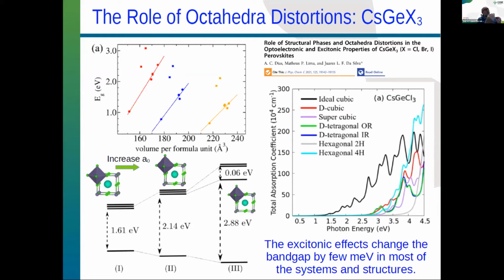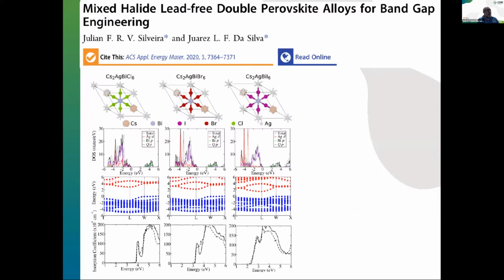However, if some of those grains stay in the hexagonal phase, they are going to contribute a larger band gap. That is quite an important point. We also find that excitonic effects play a minor role in this particular case. We use a tight-binding approach combined with DFT, as was shown yesterday by Alexandre Cavalheiro Dias. And then, of course, we were not so happy, because we wanted to move further to try to tune the electronic band structures.